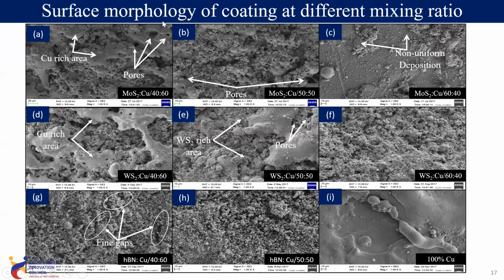This is a surface morphology of coating at different mixing ratio. It is observed that when we are changing the mixing ratio, there is a change in morphology. When we are using a high amount of MoS2 and low amount of copper, basically copper works as a binder. So if we are using a low amount of copper, MoS2 is basically an insulating material. So with a low amount of copper and high amount of MoS2, the electrode becomes insulating, less conductive. If it becomes less conductive, more insulating, it becomes difficult to deposit the metal on the workpiece surface. So non-uniform deposition was observed.